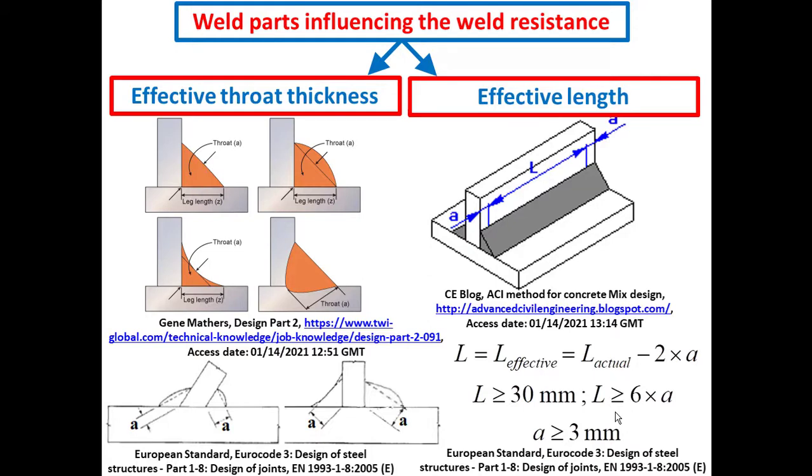This length should not be less than 6 times the effective throat thickness, which should not be less than 3 millimeters, as indicated by the Eurocode 3 standards.